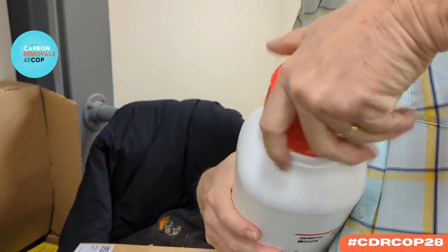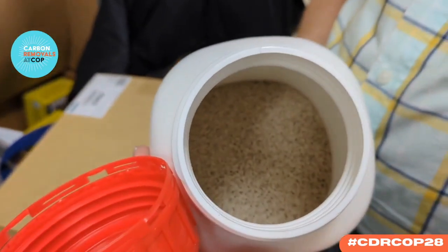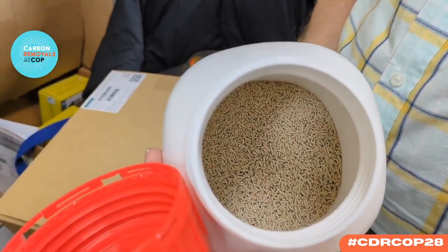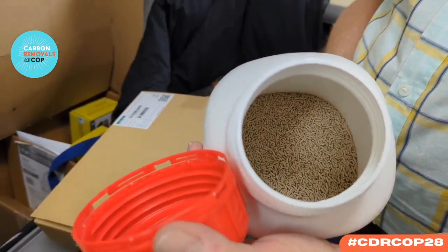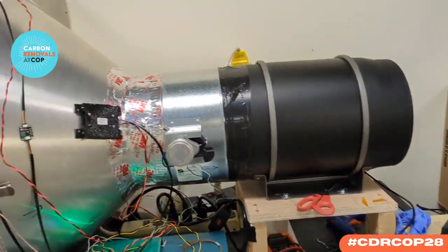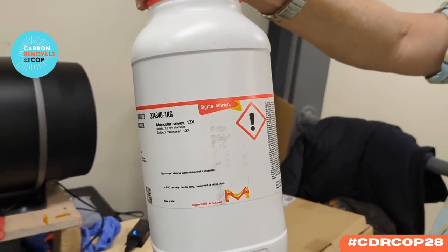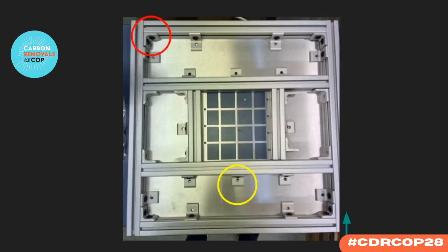And we kind of knew going in it wasn't going to do a great job, because the people that are the experts in the field have told us that it's good, it absorbs CO2, but it absorbs water even better. And what happens is when it absorbs the water, that kind of blocks all the little channels that are supposed to be collecting the CO2. However, we thought we'd be happy if it just collects a little bit of CO2. And that's what we call our Hello World demonstration.